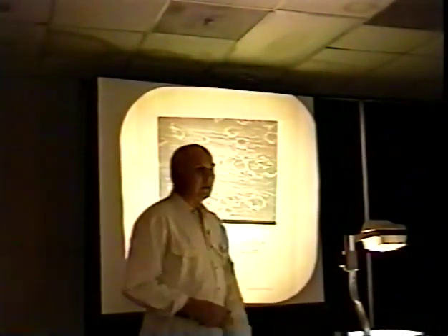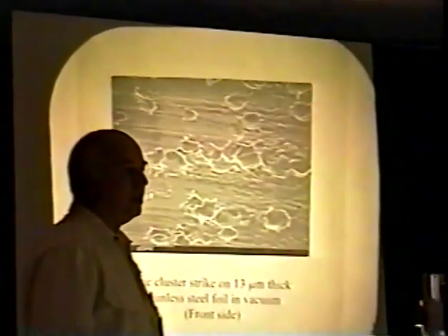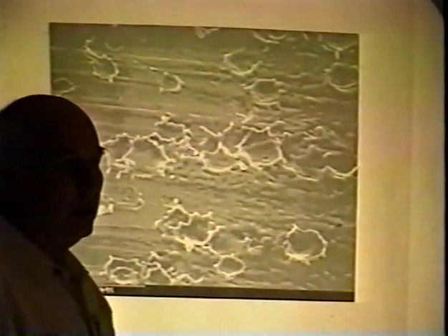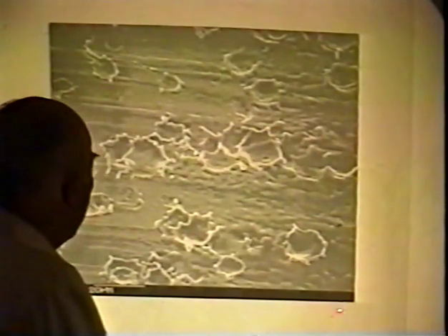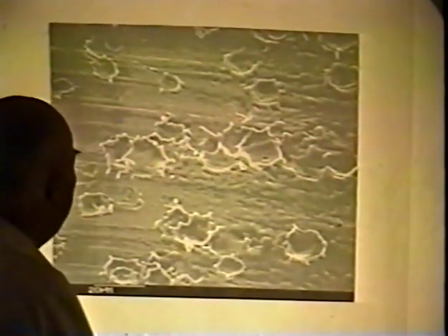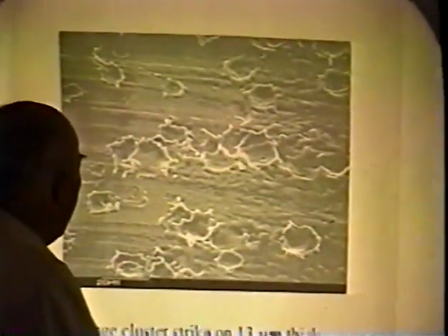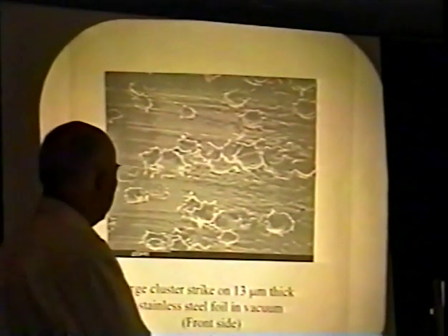Now, if you change your witness plates to materials with a much higher melting point, for example stainless steel, titanium, tungsten, molybdenum, anything you wish, you'll get a crater, depending upon the conditions, that's a lot larger, and most often flatter.